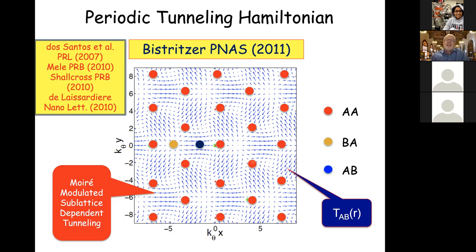It's determined by symmetry and by the fact that the two layers are separated by a distance that's larger than the lattice constants within the layers, and that property causes everything to vary slowly in space. So the electronic properties of the twisted bilayers depend only on actually one number, which is the interlayer hopping. Really, it's two numbers, the interlayer hopping and the twist, but it turns out that it's only the ratio of those two numbers that matters. And so the strength of the interlayer tunneling basically defines units for twist angle.